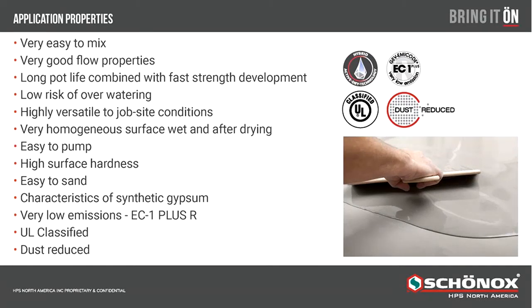It's a very homogeneous surface when wet and after drying. You'll see that when the cure process happens. Very easy to pump. We've had some very good success this year with pumping these two materials. Flows very well for those type pump systems. High surface hardness. We're getting 5,800 and 6,200 PSI compressive strength.